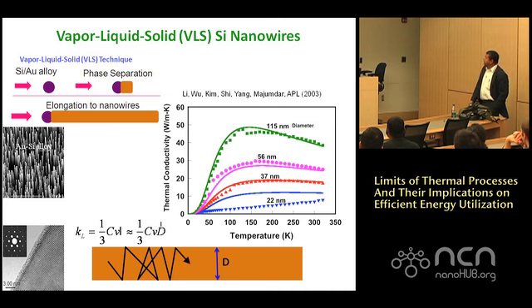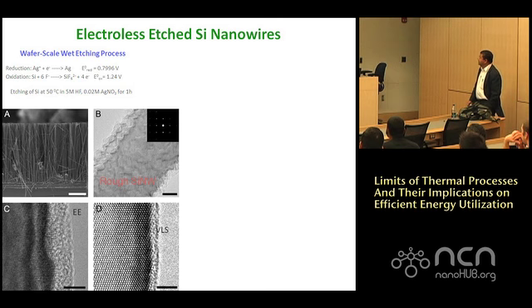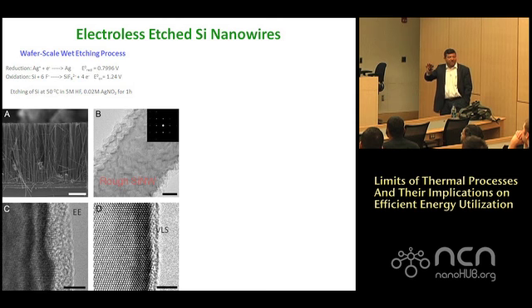So serendipitously, my colleague here, Peidong Yang, was developing these other nanowires for photonic application, for photovoltaics, by taking a silicon wafer and, instead of growing the nanowires, actually etching it. The pictures have not come out right. Using the electrochemical etching process, the electroless etching process, you get roughened nanowires. And these are still single crystal. This is VLS, very smooth surfaces. This is the roughened wires where there are jagged surfaces. And we said, let's just put it out there and see what happens.